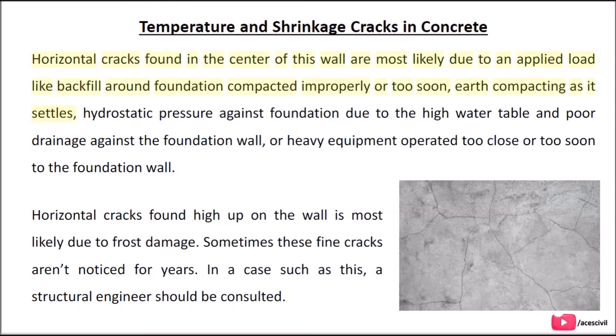Horizontal cracks found in the center of the wall are most likely due to an applied load — like backfill around the foundation compacted improperly or too soon, earth compacting as it settles, hydrostatic pressure against the foundation due to a high water table and poor drainage, or heavy equipment operated too close or too soon to the foundation wall. Horizontal cracks found high up on the wall are most likely due to frost damage. Sometimes these fine cracks aren't noticed for years, and in such a case a structural engineer should be consulted.